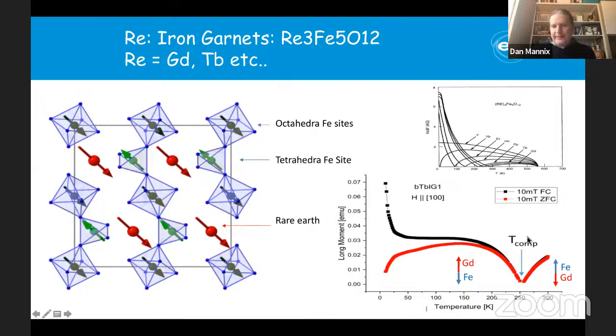At very high temperatures over here, it's the iron that orders and it's dominating. So the iron below the Néel temperature has the strongest magnetization. The gadolinium is actually very weak, but as you cool down, I'm showing the temperature dependence here, the magnetic moment of the gadolinium or the rare earth grows as the temperature goes down, and eventually it reaches a point which is called the compensation temperature, around 250 Kelvin, where these magnetic moments actually cancel. So there's no longer any magnetization measurable at all. It goes down to zero. That's because all the magnetization is equal and opposite. As you continue to cool the system, the gadolinium eventually takes over. It dominates the magnetization, so that will then align with a magnetic field if it's applied. It's the gadolinium moments that basically dominate at lower temperatures.